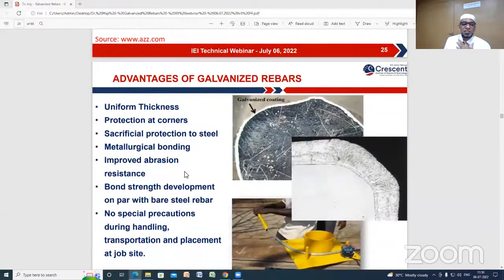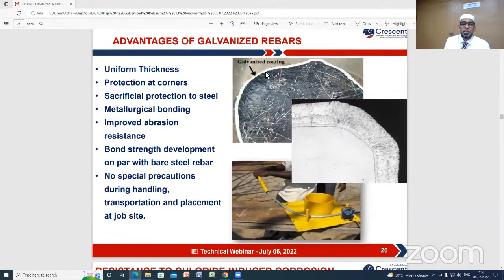So what are the advantages of the galvanized rebar? It offers a uniform coating thickness. These are cross-section SEM pictures showing uniform thickness and protection at corners. Even if you bend, nothing will happen, since the mechanical properties of the zinc are almost even, in some aspects more than the steel. So nicely, the curvature will happen without any crack, and there is improved abrasion resistance.